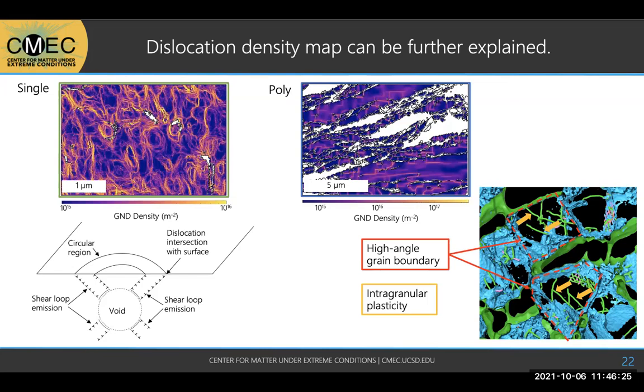And then in the polycrystalline sample, the regions of higher density are actually within larger grains, and those would be at sub-grain boundaries. And so when we look at the simulations that correspond to that, that's the bottom right image there. That red dashed line would be the larger grain boundaries, along which failure occurs, as I've been describing. But within those grains, which are pointed out by arrows, you see these are actually dislocation lines, and that means that you have plastic deformation occurring. That's what I mentioned at the very beginning of the talk. And so we have evidence of both intergranular failure, so between grains, and intragranular plasticity, so within the grain. So it was a really cool way to be able to tie everything together. Next slide.